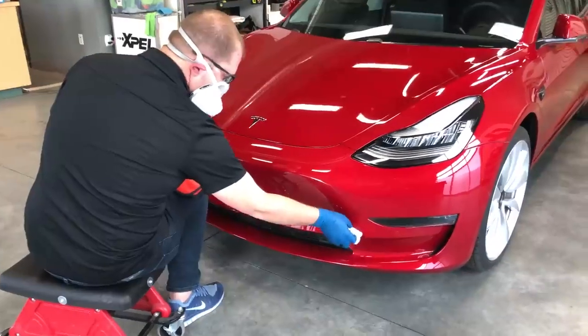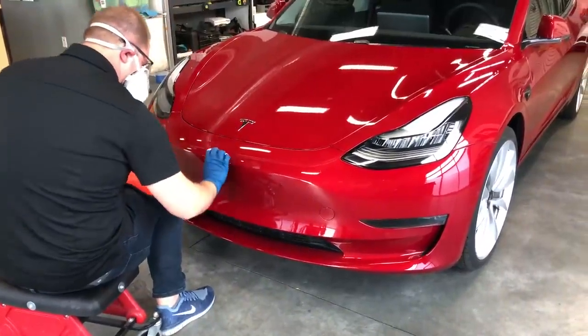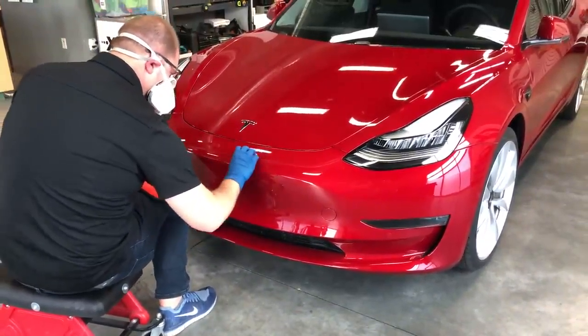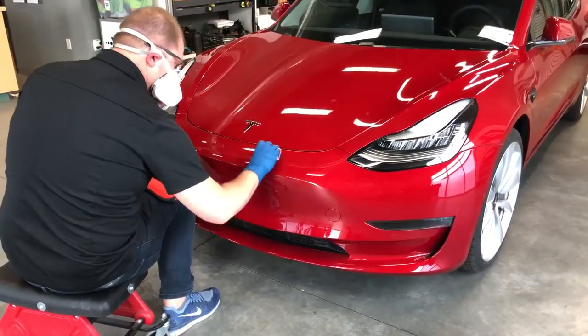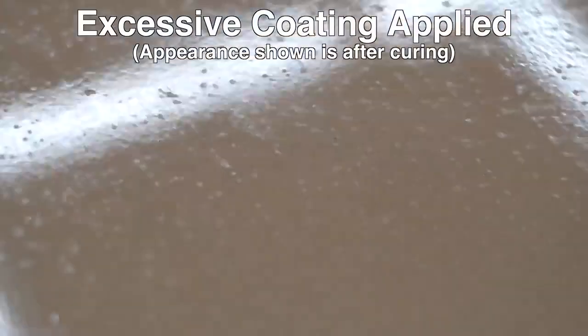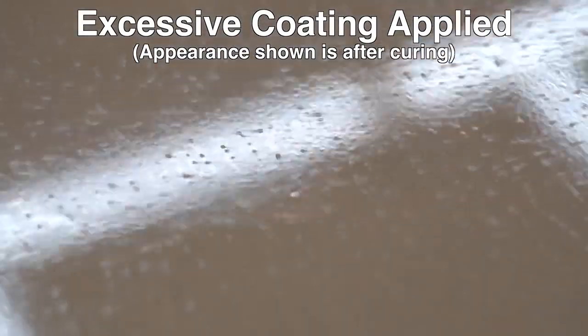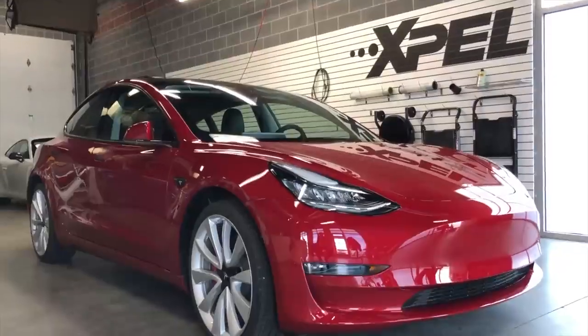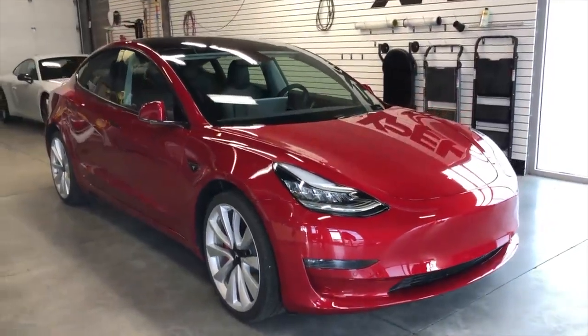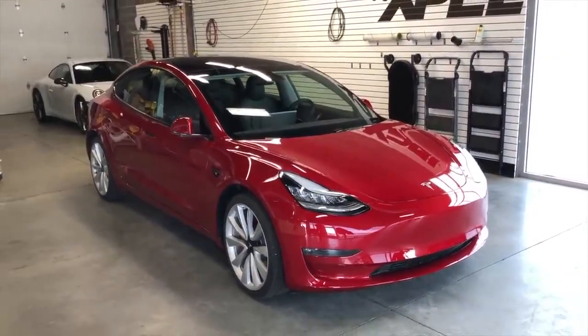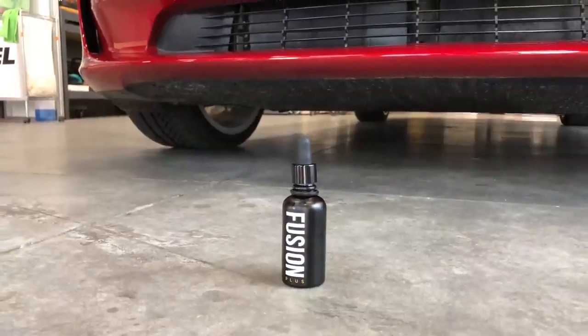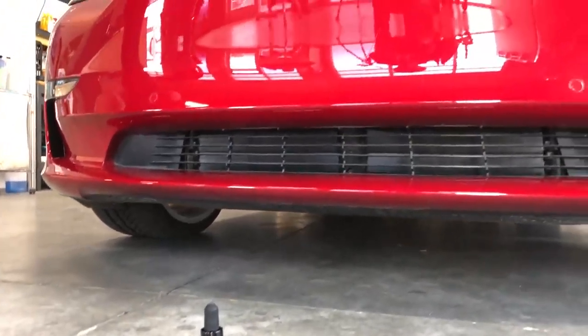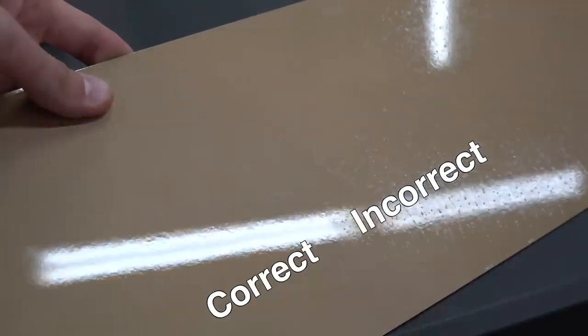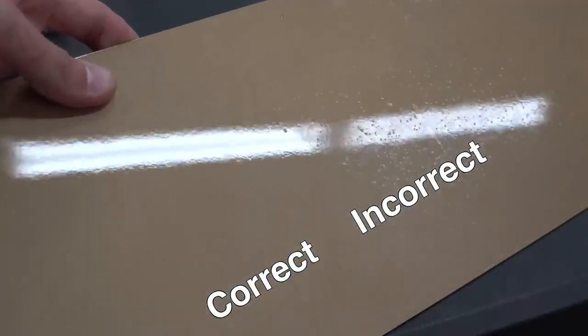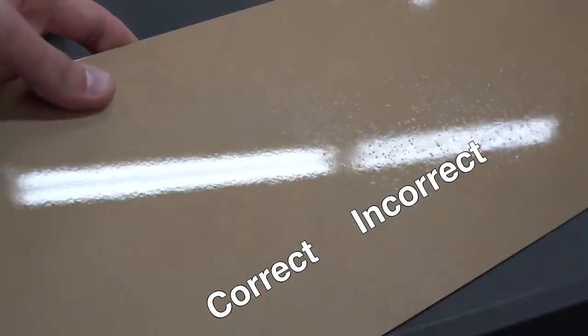When applying the product, things like humidity, temperature, and how much you apply can all change how quickly the product starts to flash off, which alters the exact time you should wipe the surface down. If you apply too much product or to a dirty surface, you can leave behind a streaky appearance, drips, or seal dirt to the surface. Once the product has cured, it's difficult to remove, and also difficult to tell if you've fully removed it. To remove it requires polishing, aggressive compound, or worst case, wet sanding. I've shown some panels here with what it can look like when the product has not been properly applied versus when it has been installed correctly.